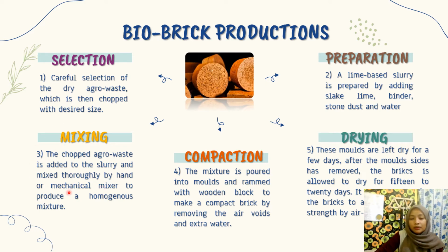The mechanical mixer is used for large production of the biobricks. If not, they will just use hand mixing. Next is compaction. The mixture is poured into molds and rammed with a wooden block to make a compact brick by removing the air, voids, and extra water. The last one is that the molds are left to dry for a few days, about 1 to 2 days, and then the brick is allowed to dry for 15 to 20 days. Actually, the biobricks will take about 1 month to reach their strength by the air drying method.